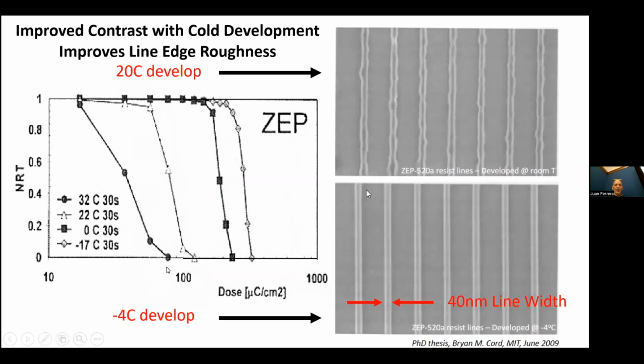And interestingly, not only do you get increased contrast, or because you get increased contrast, maybe, if I make 40 nanometer lines in ZEP and develop it at room temperature, I get this ragged stuff here, these not very nice lines. If I do the same thing at 0 degrees C with a higher dose, I get beautiful, nice, sharp edges here. And this is what we prefer to see.